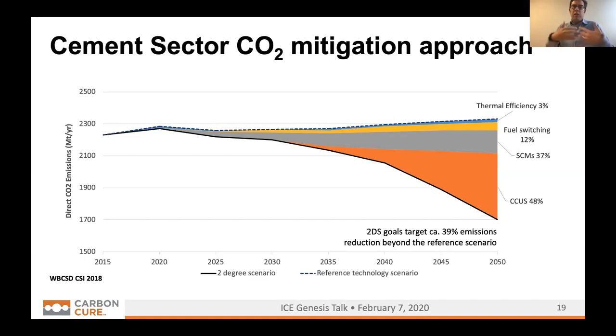And that's the emissions that will come from the calcination of limestone over the next, until 2050. They see certain levers to get the total amount of emissions down. The first 3 of them are well known. You can make a cement kiln more thermally efficient, which can make a small improvement. You can switch to lower carbon fuels. So instead of using coal, you can use something else that has a lower carbon footprint for your cement kilns, and that can make about a 12% reduction. And you can look at secondary cementitious materials, things like fly ash and slag, that will allow you to use less cement clinker in your concrete. That will have a bigger impact.